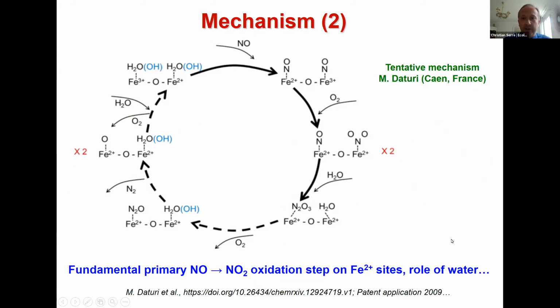And this is a putative mechanism proposed by my colleagues. Here the arrows in full line are what has been seen by operando, and in dot line what has not been seen yet, but is based on what is known in literature with zeolite, for instance. And so it is involving the 2 iron sites. It's a bit complicated, but then you have the role of the different species. For instance, oxygen here for oxidation of NO into NO2, then formation of N2O3 with water, then oxygen is leaving. Then at this point, nitrogen is leaving, and then again with the water and oxygen, the sample is regenerated.